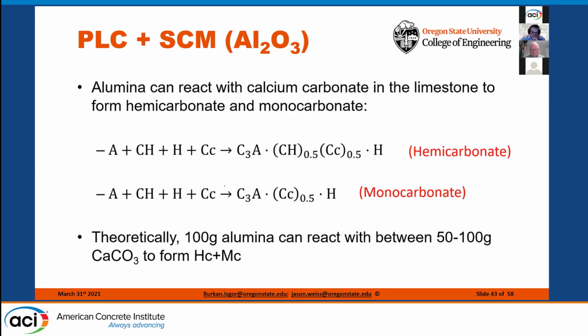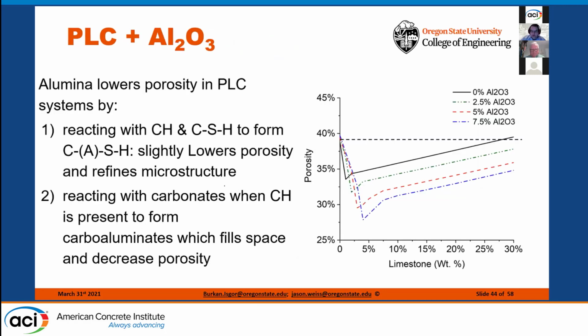However, when we add alumina, we have some of those additional reactions that we were talking about. If we add alumina, this is the overall porosity that we're going to start to see in the system. What we're going to notice is that the calcium hydroxide and CSH are going to form more CASH phases. They're going to form more calcio-alumino-silicate hydrates in the system. This is going to lower the porosity. So if we had just a straight system without additional alumina, we'd be at this black line. But as we add more and more alumina into the system, there's more alumina to react with the carbonates, and we can see this porosity really decrease substantially, right? And we can see this really cause a great impact.